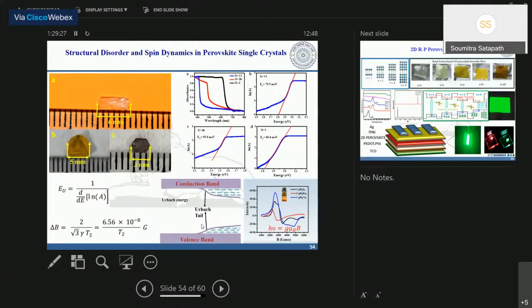To answer that question, we did temperature dependent ESR spectroscopy. Temperature dependent ESR spectroscopy gives you the Landé g-factor. It gives you the dispersion of the Landé g-factor as a function of the magnetic field. From there, we have calculated, and found out, that the strong spin orbit coupling in this material is actually responsible for this large disorderliness in this bromine-based single crystal. And this spin orbit coupling strength was calculated to be very large in comparison to other similar systems, and that matches with the theoretical calculations.